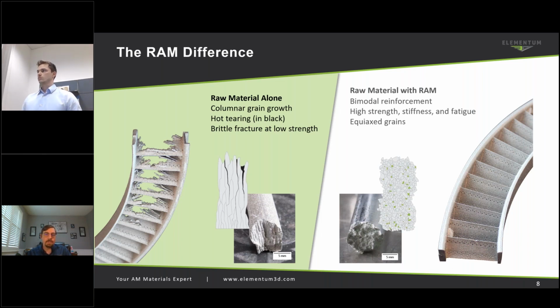In a lot of these alloys, the difference here is when we add these nucleation sites, we can actually form materials that you couldn't otherwise, and we get properties that are very similar in the vertical to the horizontal. And then in addition, we get the benefits of these ceramic particles distributed throughout the metal, which we'll talk about here in a minute as well.